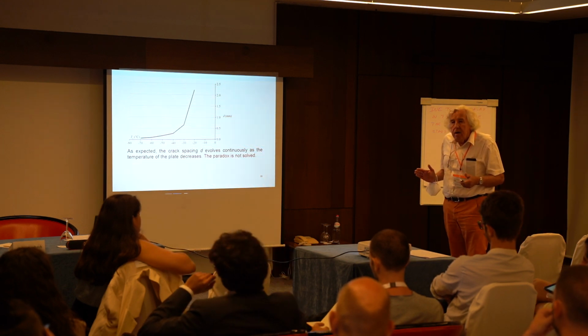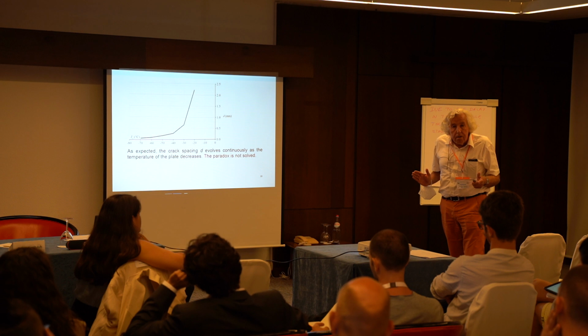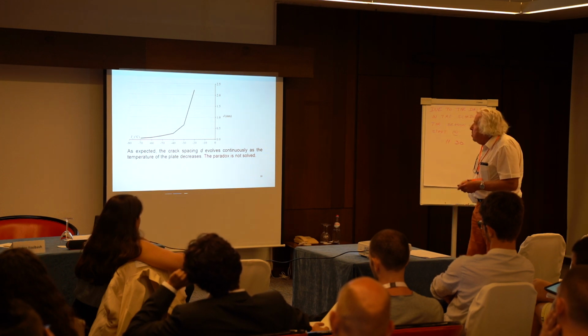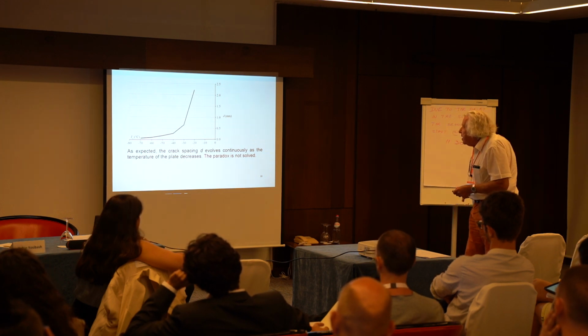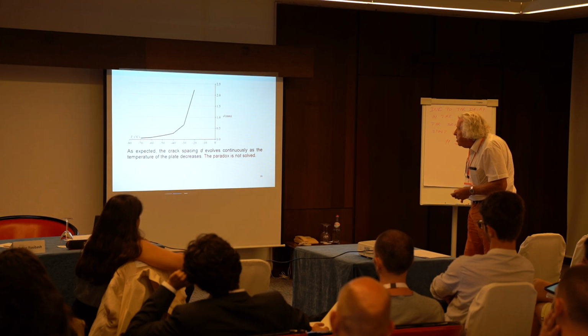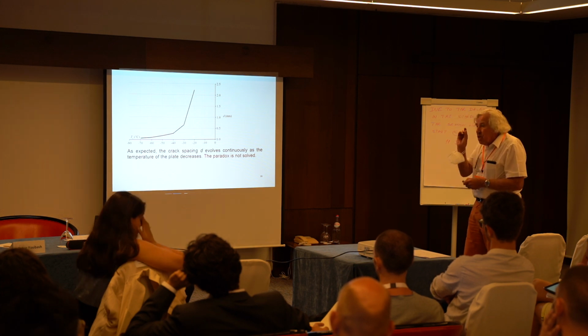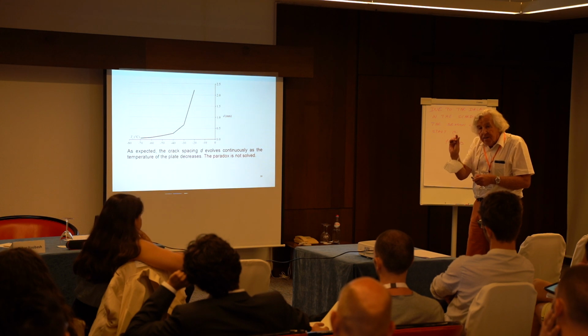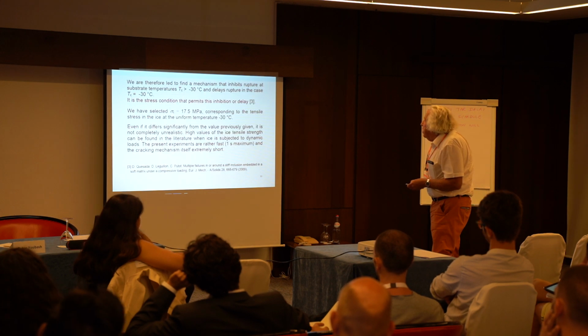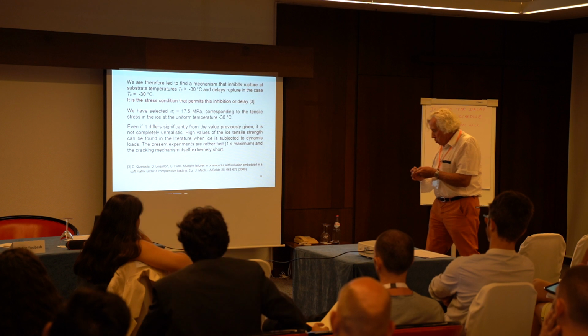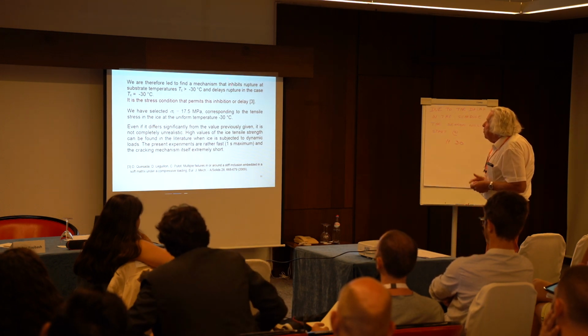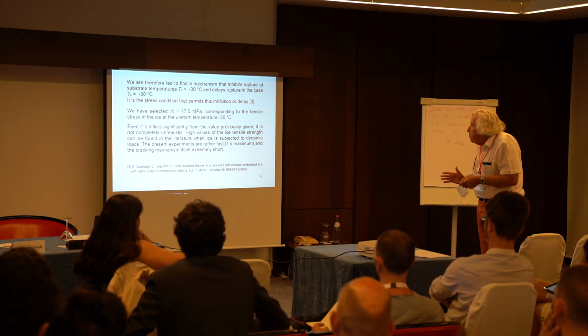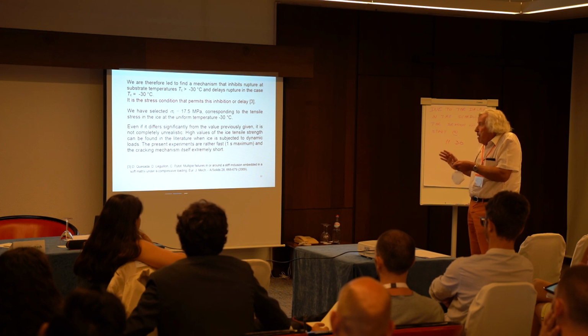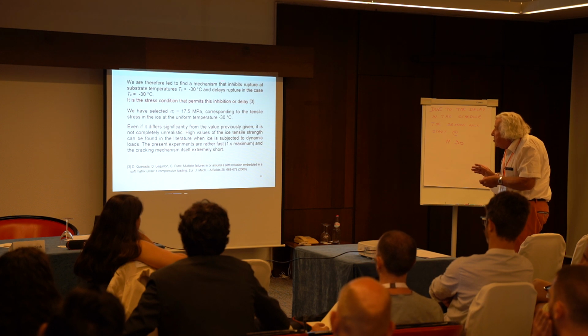But of course the paradox is not solved at all, because remember the paradox, finally we have something like that, but for minus 30 degrees we have a very, very tight pattern of cracks. So what we have to do is to find a mechanism that inhibits rupture until the temperature reaches minus 30 degrees Celsius. So the rupture should be delayed until this temperature.